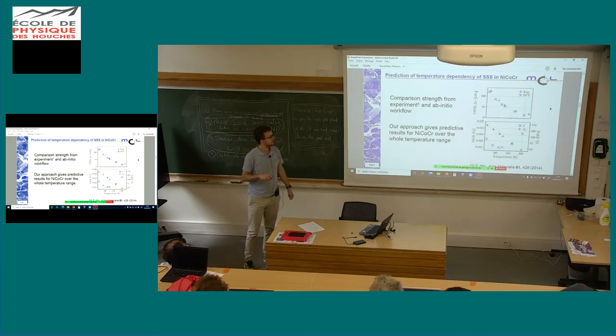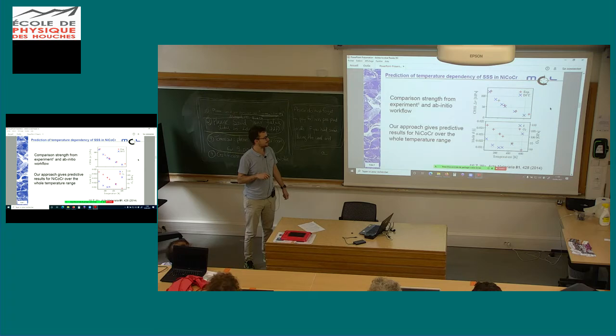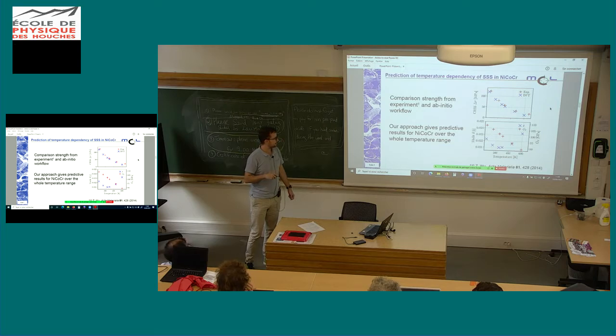So what we did is we calculated now with our workflow this strength. This is then the intrinsic property. It's called the critical resolved shear stress. So basically the shear stress that is needed for moving a dislocation. And we compared it with trustable experimental results. And we also compared it by using experimental results for the model. And we really found that we actually can predict for this nickel cobalt chromium alloy the strength throughout quite a big temperature range.